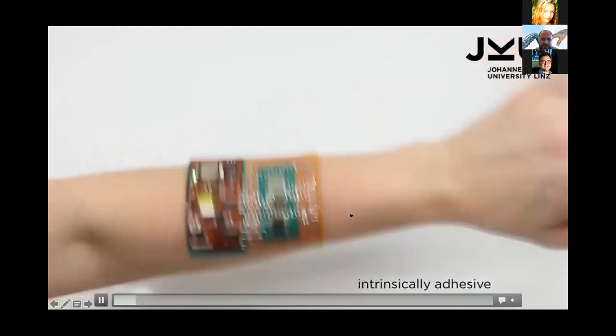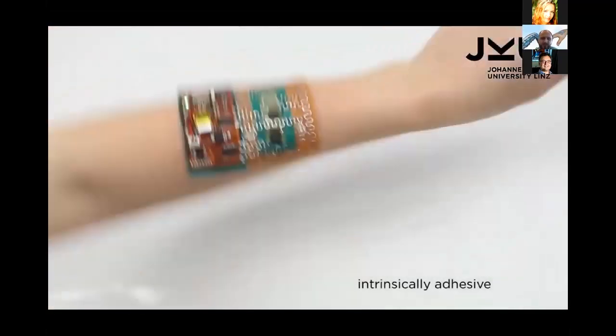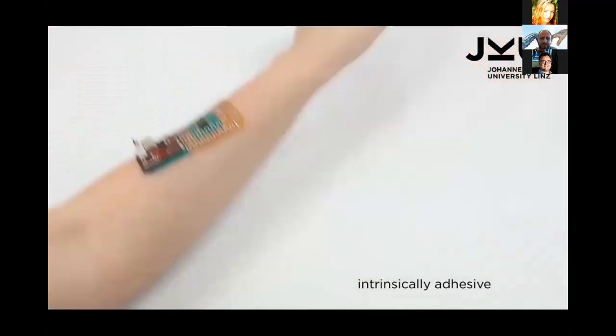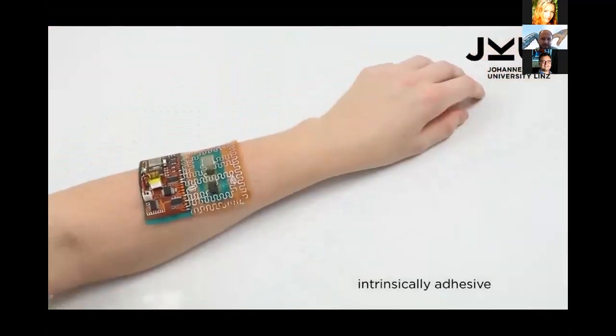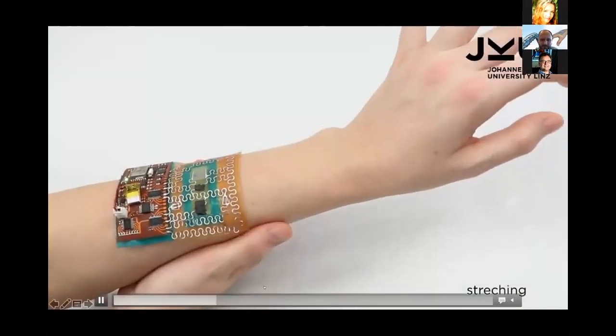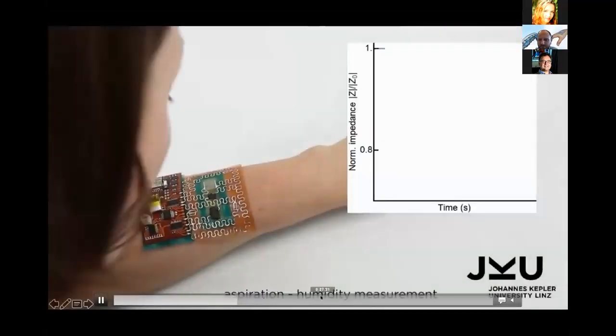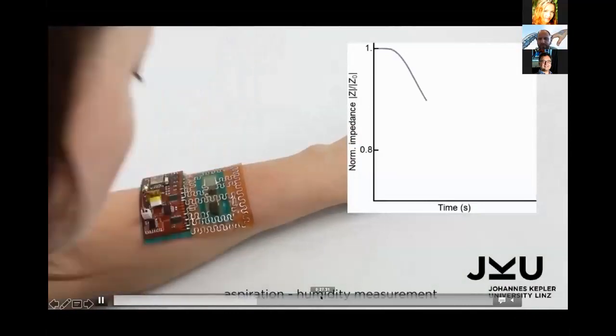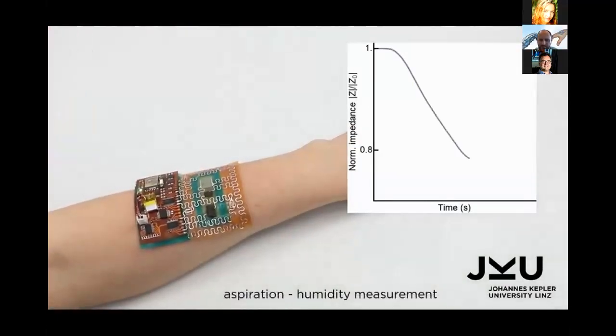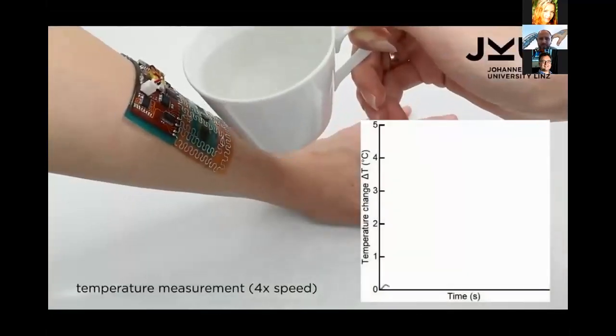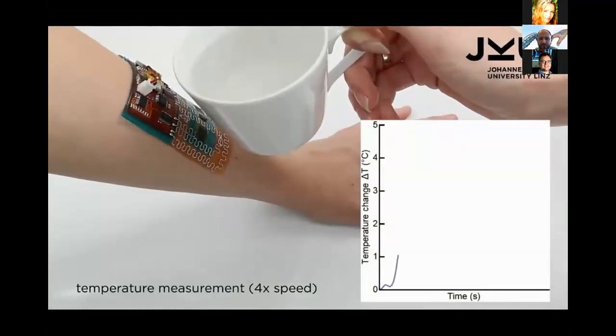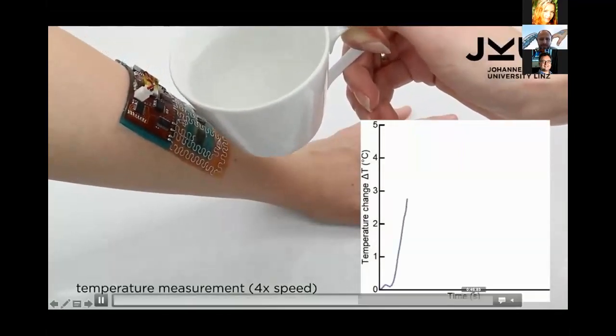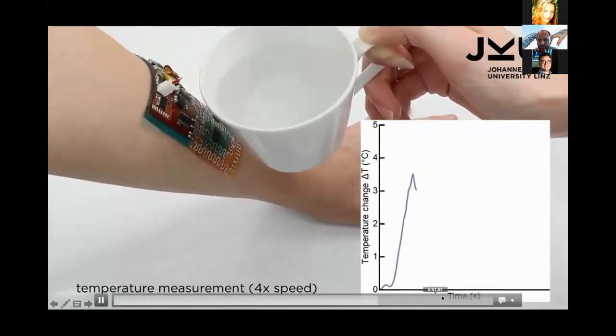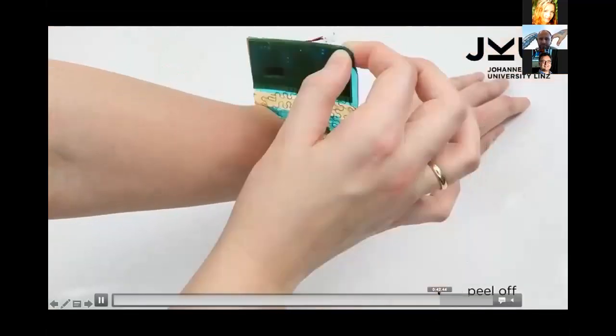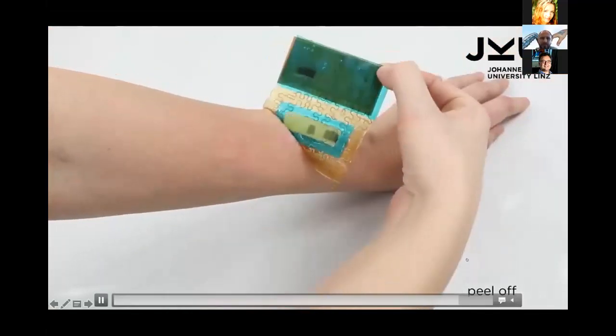The advantage of this gel is that it also adheres on its own on the skin, so it doesn't come off. It feels like a regular medical plaster. You can put it on, you can measure. That video just shows that the functions work. So if Melanie blows on it, she changes the humidity. So the signal drops. And you can, of course, also just measure temperature by using a hot cup, for example. You see that the temperature rises in the vicinity of the patch. And of course, you can do the same with strain. I should speed this up a little bit. And once you're done, you can very easily peel off the device from the skin, and it doesn't irritate your skin.